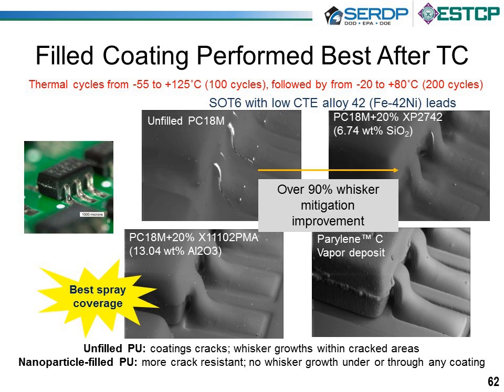And, of course, the proof of the pudding comes when you look at an assembly. Flat coupons are pretty easy to coat uniformly, but in an assembly, you've got vertical leads, you've got horizontal features, you've got corners, you've got edges. This is the unfilled version of the coating, and after some coating and some thermal cycles, we saw some crack formation where the coating was thin. The cracks propagate along the side here and on down.